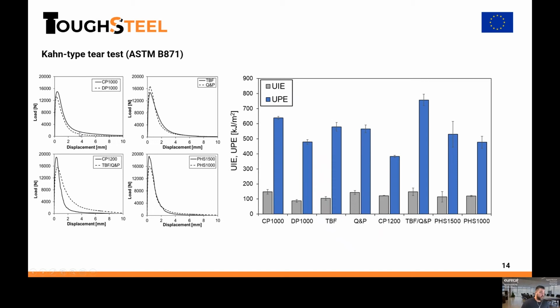Again, some results of this kind of methodology, the Kahn-type tear test, for advanced high-strength steels. Again, we can see the methodology is feasible. It can be applied to this kind of thin metal sheets. So we can separate this unit initiation energy and unit propagation energy and obtain also a material ranking according to this parameter.